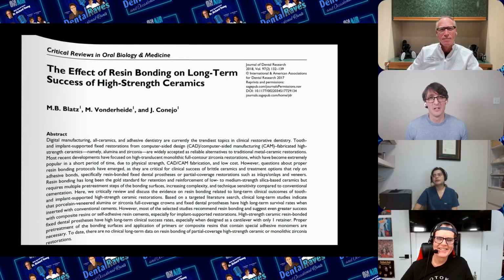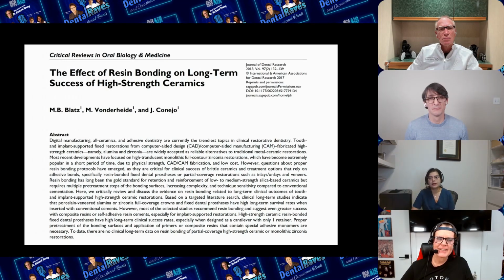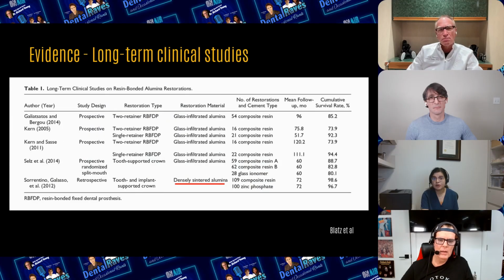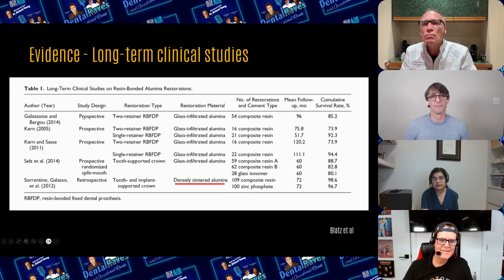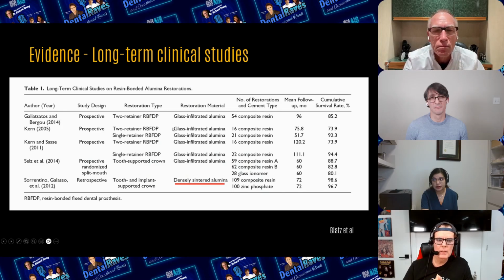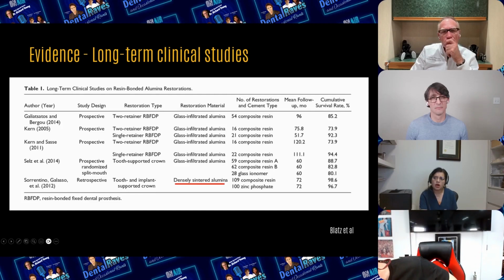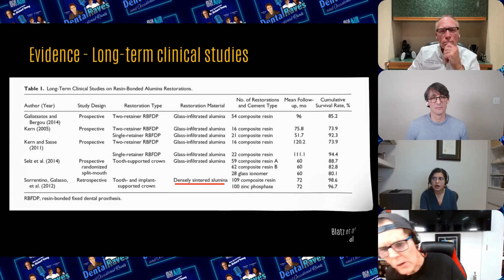So this is a critical review article by Blatz and team that was published in 2018 in the Journal of Dental Research, and basically it critiques several clinical studies published on resin bonding of ceramics, but it also discusses both glass ceramics, silica-based, alumina-based ceramics, and then the zirconia ceramics. And looking into this critical review, we can say it's recently published. So at the time of publication of this review, the long-term clinical studies existing for glass-infiltrated alumina were quite a bit, as you can tell. Densely sintered alumina, there was a retrospective study done by Sorrentino in 2012 that investigated tooth- and implant-supported crowns. But in today's topic, we are not interested as much in the glass-infiltrated alumina, but we are interested in zirconia.